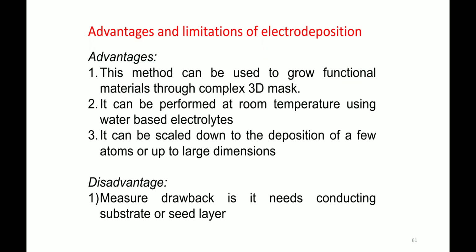So what are the advantages and limitations of electrodeposition? As I said, there are so many advantages. This method can be used to grow functional material through complex 3D masks. So you can use a complex 3D mask, which will basically be non-conducting in nature. It can act as a mask, and through that mask you can deposit different shapes of metal material. It can be performed at room temperature using a water based electrolyte. Very big advantage of this. It can be scaled down to the deposition of a few atoms or to large dimensions.